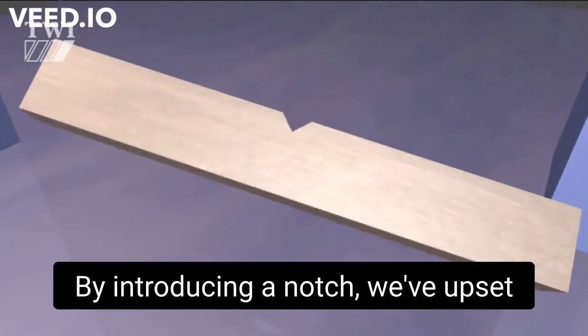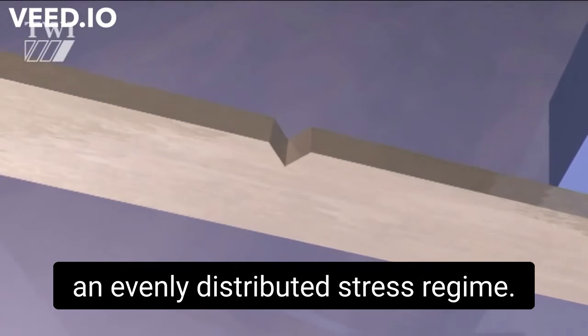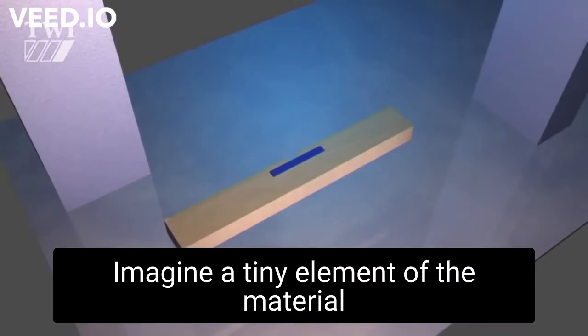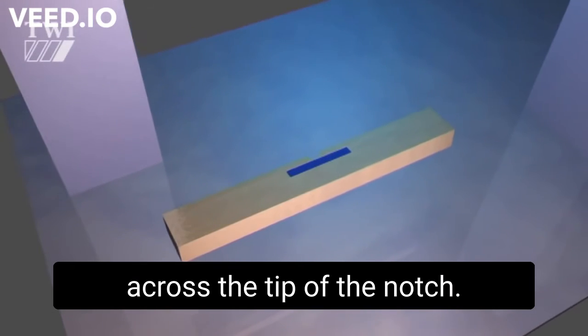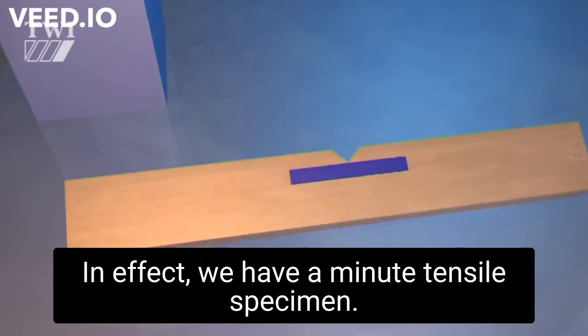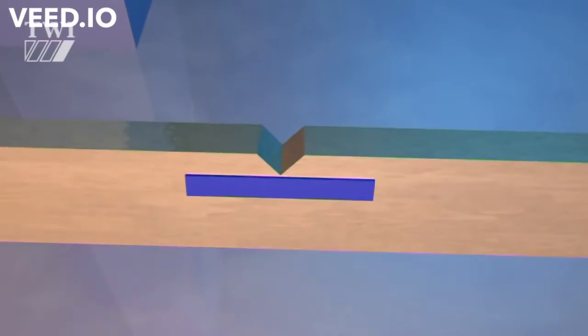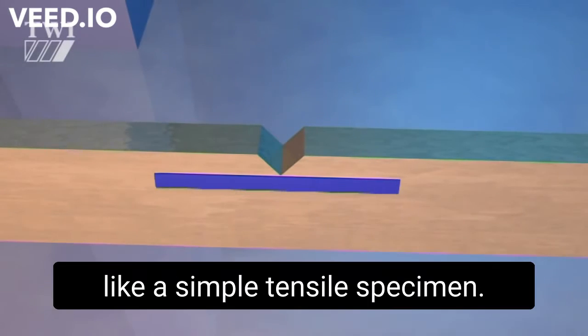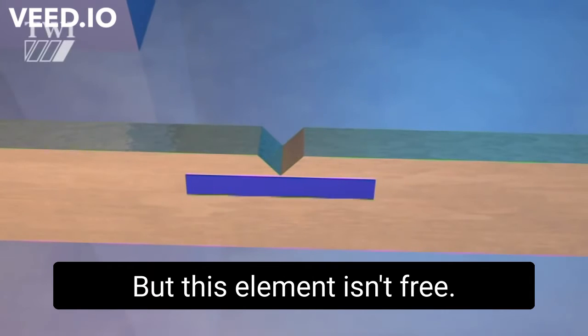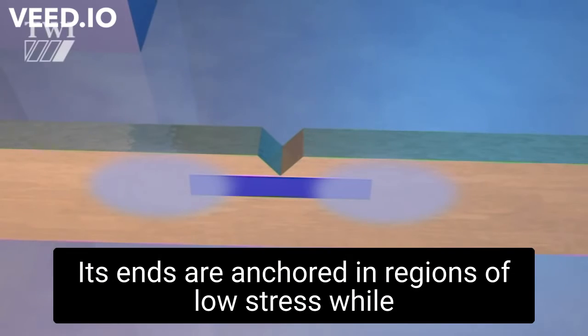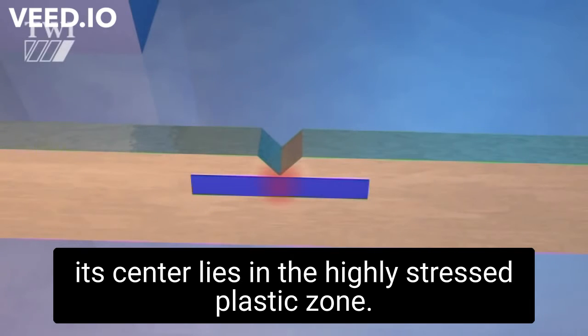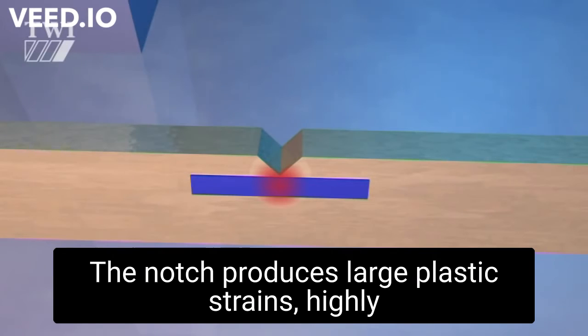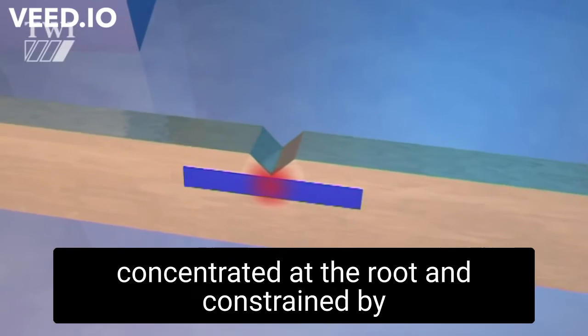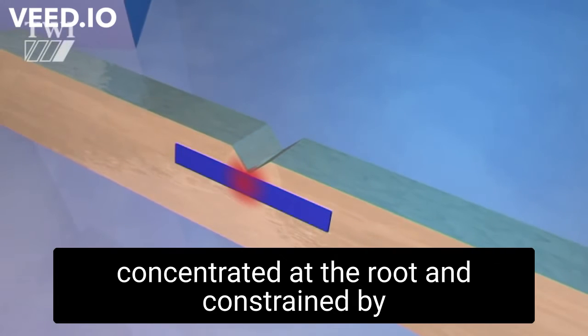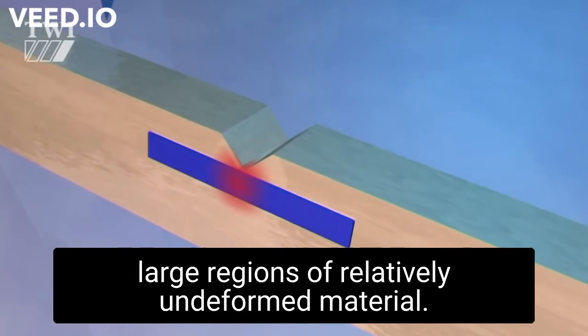By introducing a notch, we've upset an evenly distributed stress regime. Imagine a tiny element of the material across the tip of the notch. In effect, we have a minute tensile specimen. Under free conditions, this would behave like a simple tensile specimen, but this element isn't free. Its ends are anchored in regions of low stress, while its centre lies in the highly stressed plastic zone. The notch produces large plastic strains, highly concentrated at the root and constrained by large regions of relatively undeformed material.